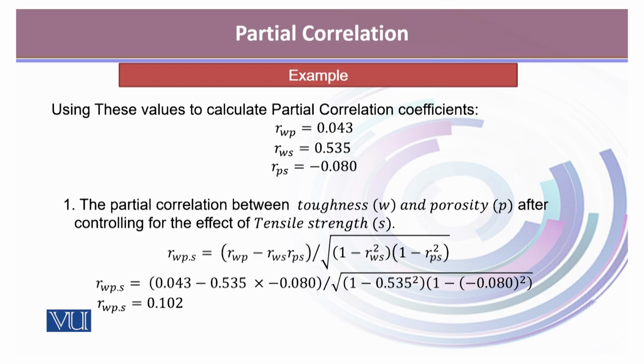measuring the correlation between toughness and porosity after controlling for the effect of tensile strength, we include these simple correlation coefficients into this formula and we get the value to be 0.102. One might notice that the correlation RWP is 0.043. But if we control for the effect of the tensile strength S, the correlation has gone up and this is 0.102. So this clearly shows that there was some effect of tensile strength on the relationship between toughness and porosity.